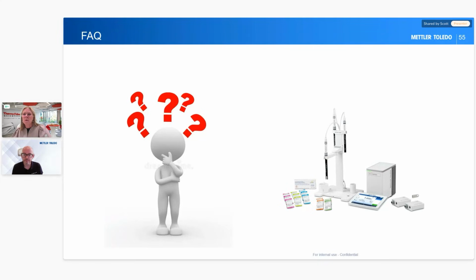Keely is asking if you're taking a pH probe out into the field, is there a minimum and maximum temperature recommended? No, not really, other than the recommended range. On the Mettler ones, we have a temperature range, which is the temperature range it will measure between, and it's normally between 10 degrees and 90 degrees, somewhere like that. So, for example, you'd struggle to use it outside in the Arctic or Antarctic. And obviously you need to keep the electrode warm before you take measurements in ice and very cold solutions. But generally, if you keep it at room temperature when you're not using it, that's the best thing.